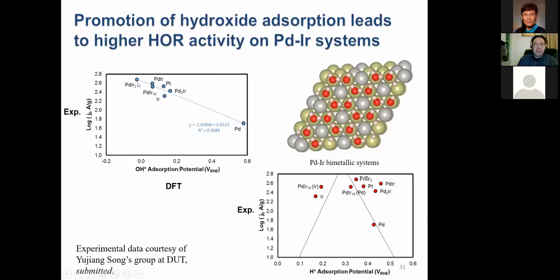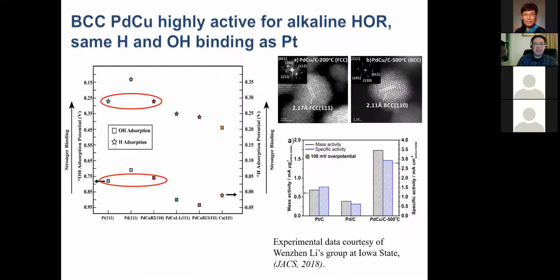And we found that there was no correlation with the binding energy of hydrogen we calculated with DFT calculations. So this is DFT hydrogen adsorption energy versus the experimental rate of reaction. And if you want, you can squint. I drew a volcano in there, but if I didn't draw that, your eye would never have seen that in the first place. You'd say that's a bunch of random red dots. So the hydrogen binding energy was not a good descriptor, but here it was pretty linear in hydroxide binding energy. Obviously there's noise in these experiments, but there seems to be some hint hydroxide adsorption is predicting what's a good catalyst.